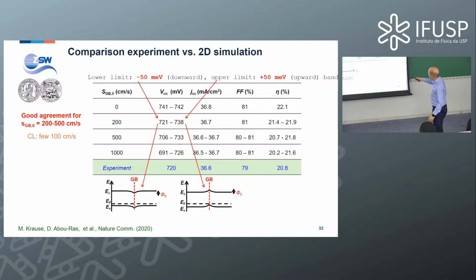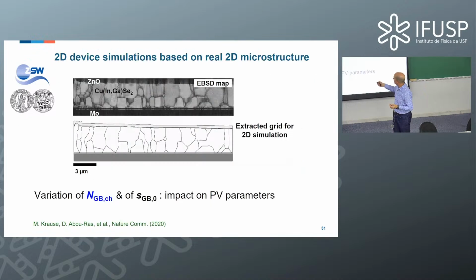Right? There is some discrepancy here between the fill factor values of the simulated ones and the experimental ones, but this is because the model was not so perfect in terms of the contacts. Right? So this is also why here we have some deviation. Okay? So you can see there's a confirmation here, but when we actually ended this project, we said, what is true in 2 dimensions must not be true in 3 dimensions, because we look at a 3-dimensional object, right?